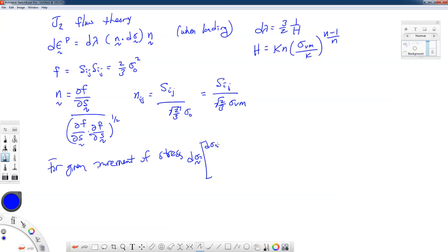So in general, we could have a multi-axial state of stress. I'll write a few of these in here. Be symmetric. But we take this d sigma, again dotted with our unit normal based on this matrix, multiply it by this matrix, and then we multiply it by d lambda. It's based on our plastic tangent modulus, and now out pops our plastic strain increments.